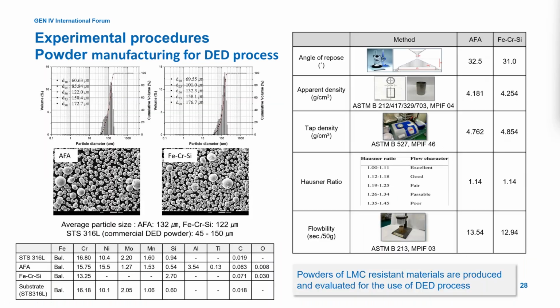In this study, AFA and iron chrome silicon alloys were manufactured into powder form. For the comparison group, commercial STS316L powder was used. These powders were characterized for their flowability and confirmed to be suitable for the DED process.